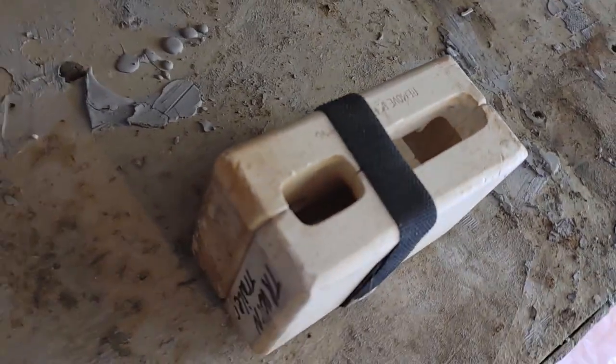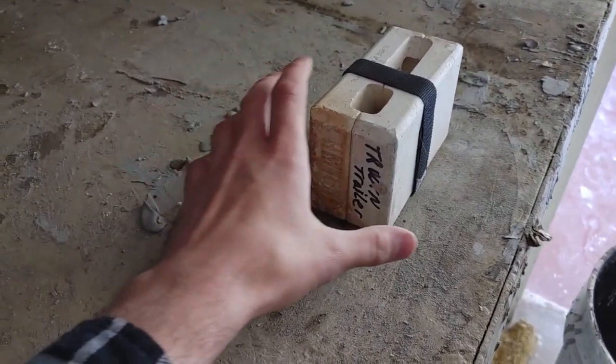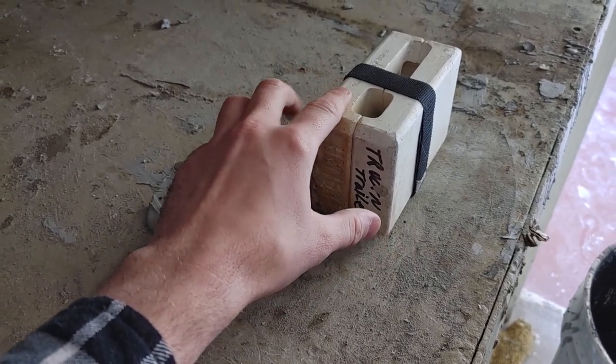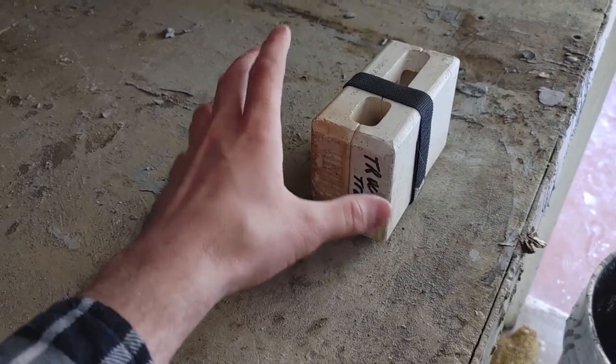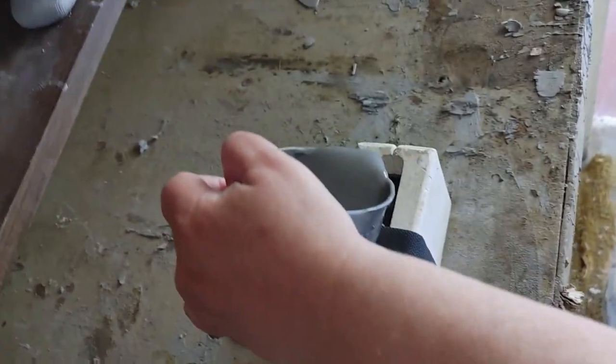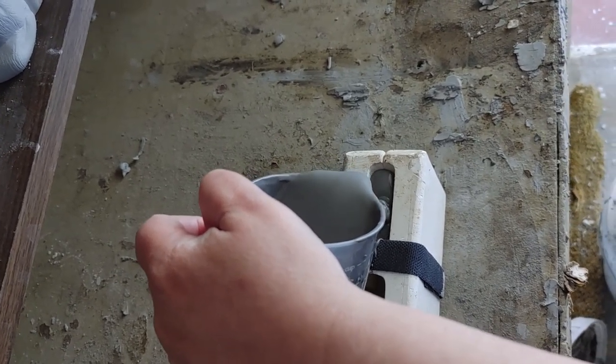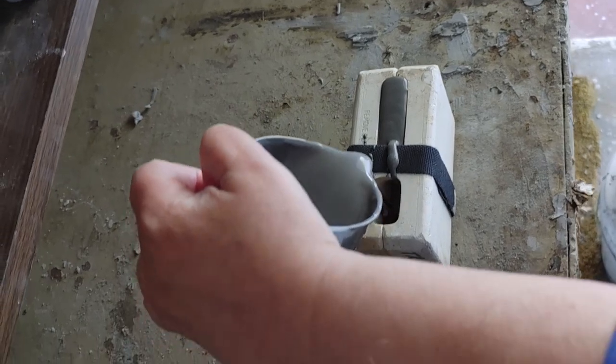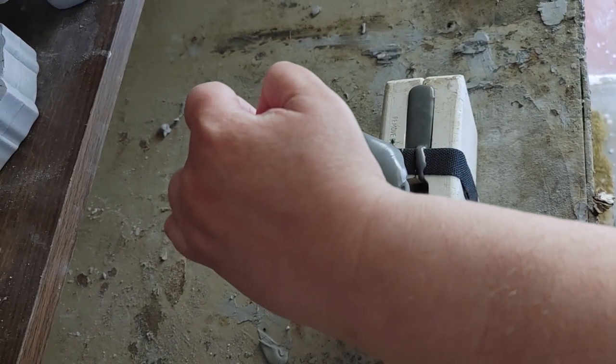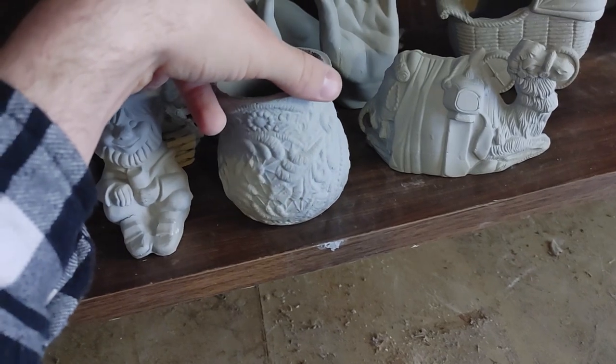Okay, now the two pieces kind of fit together like a puzzle piece. And what's going to happen is we're going to pour in some of this slip in these two notches right here. And then we're going to leave it in there for a certain amount of time until the moisture, the... what's this made out of? The ceramic? That's plaster. Plaster. The plaster is going to absorb the moisture in here. And that's going to cause it to gel. A certain amount of it will. But then the inner parts we're going to actually pour out. And it's the shell, like I said before, that's left over that kind of takes the design.